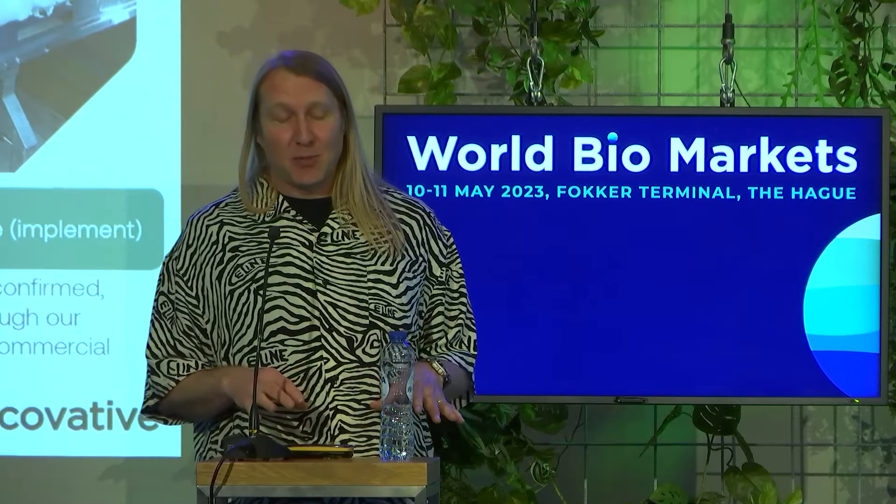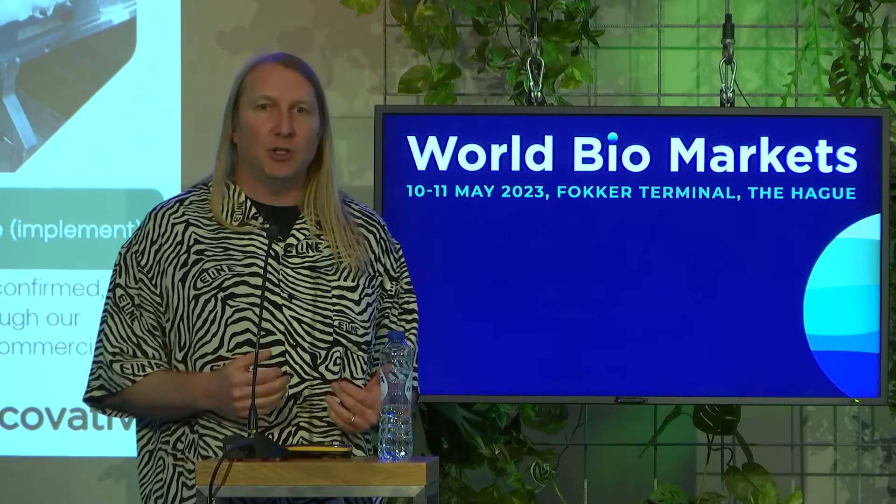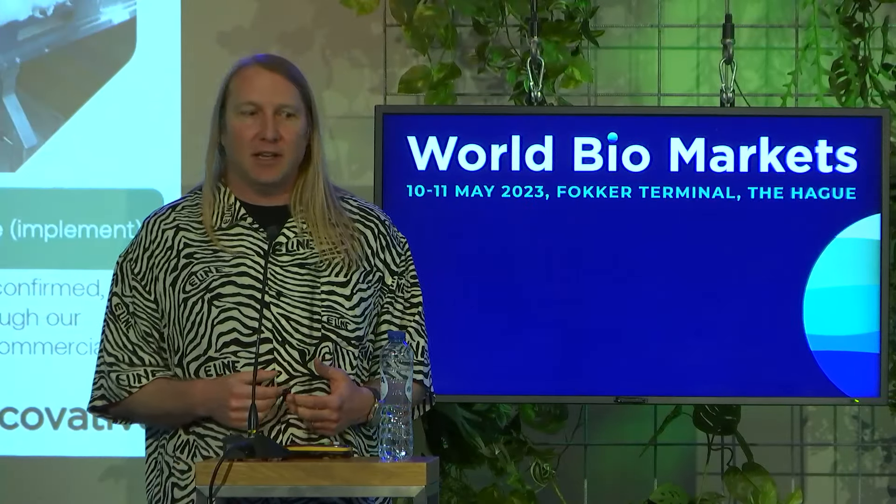To give you an idea of how we develop new materials, this is a simplified three-step approach. A brand comes to us wanting a material with characteristics X, Y, and Z. We have a mycelium strain library, and those strains have relevant characteristics. We put them through a high-throughput screening method, running them through a variety of environmental conditions to see what results we get. We take the hits from that screening and scale them up to prototype scale, so customers can make the intended products and do performance and durability testing. If results are good, we scale up to pilot in commercial quantities; if not, we go back through the design-build-test cycle.